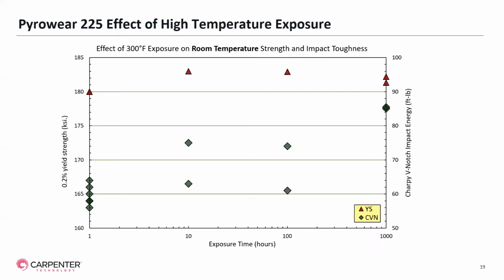We were pleasantly surprised to see what the effect of the Charpy V-notch impact energy was on this long-term exposure, as evidenced by the green diamonds, where even after 1,000 hours at 300 degrees F, our room temperature Charpy V-notch impact energy was at 85 foot-pounds, greater than what it was when we started at about 60 foot-pounds.